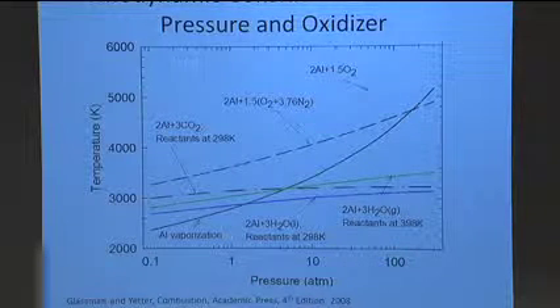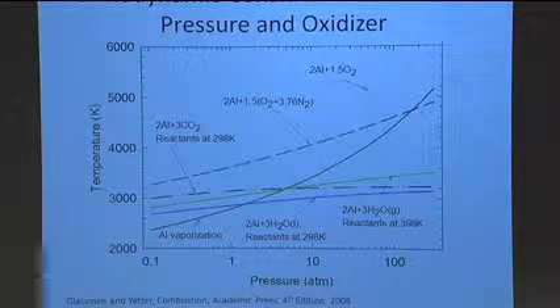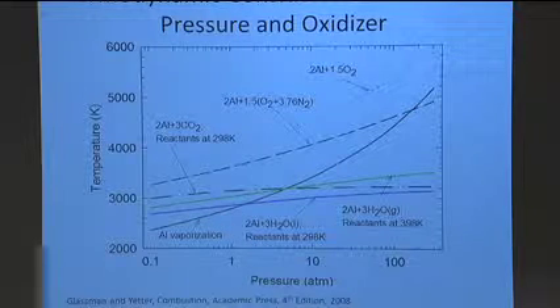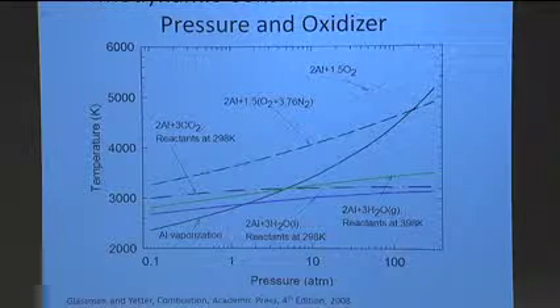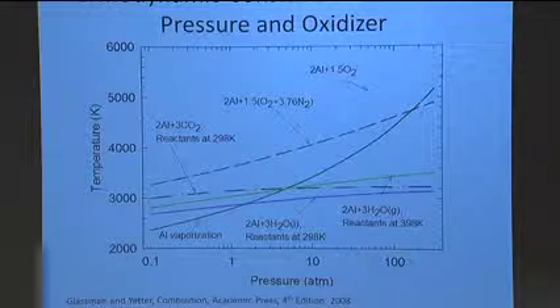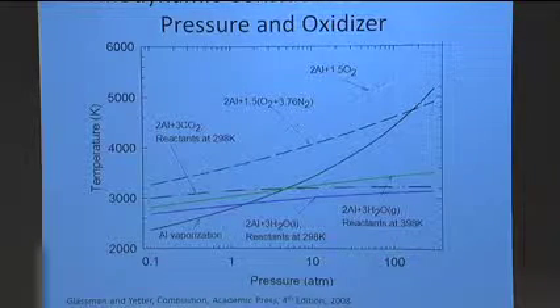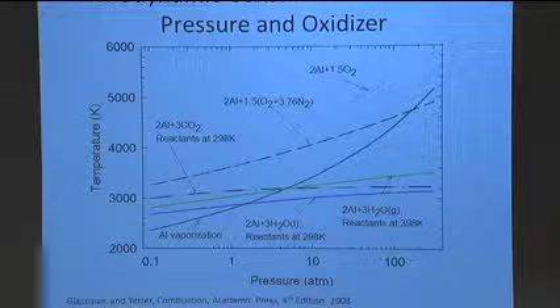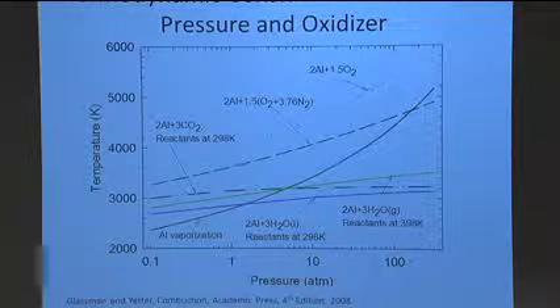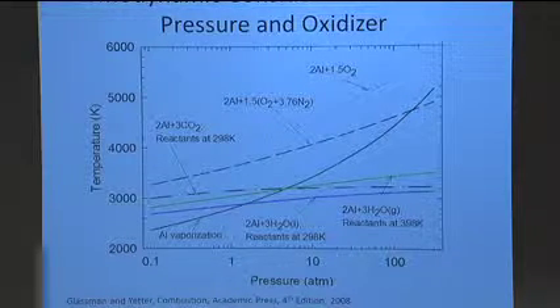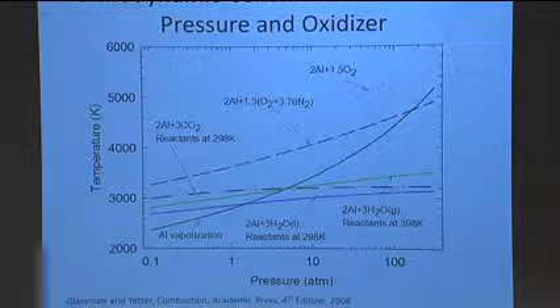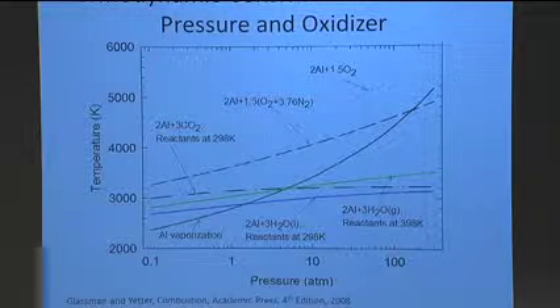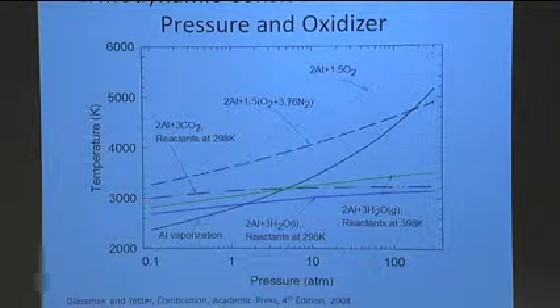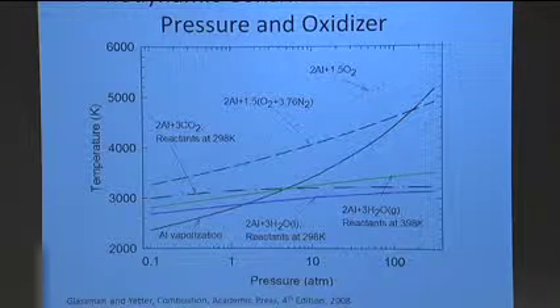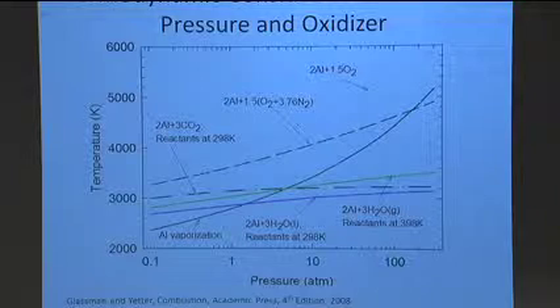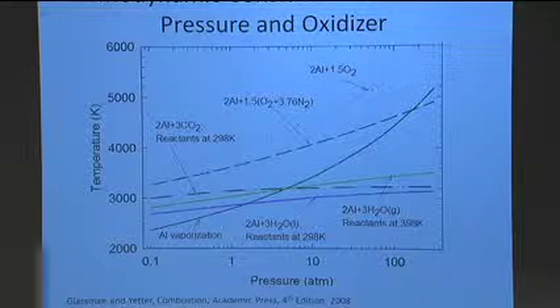Okay, as I start to increase the pressure, one thing you start to notice is the vaporization temperature goes up at a higher rate than the flame temperature itself. So theoretically, I can get to a situation above, say, 100 atmospheres, where now the reaction temperature is less than the vaporization temperature. So no longer do I have the heat from the reaction coming back to the surface to vaporize the aluminum. And so I'm going to see at very high pressures potentially aluminum change from a vapor phase to a heterogeneous reaction. And this is in oxygen.